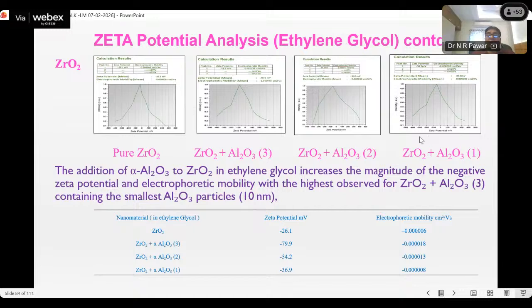Now what is our result? This increases the magnitude of the negative zeta potential. Whether the value of the zeta potential is positive or negative does not matter, but a higher positive or higher negative value indicates more stability of that hybrid nanofluid. It is observed that the zeta potential values are negative, but the values are higher.